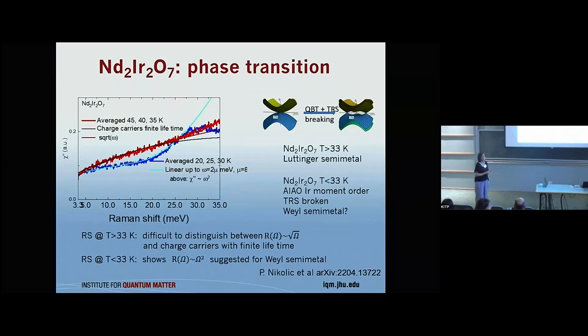Oh, I see. But then you can have the temperature larger than this chemical potential, and there are very specific predictions for, say, the temperature dependence of conductivity for both a Weyl metal and parabolic band touching that one could test. Have you performed any transport measurements? So transport measurements have been published for this material, which we could look at. I mean, for this crystal even. So we could, and as far as I understand, they do agree. But I have to say that it's a nice thing to check, actually.